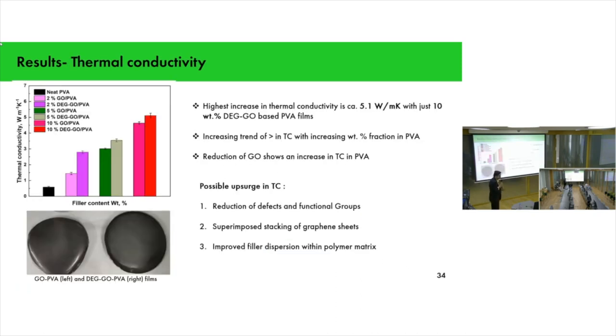So going into the thermal conductivity, our system exhibited extraordinary thermal conductivity, 5.1 watts per meter Kelvin, with just 10% filler in the DEG-based PVA system. So what's the mechanism for that? The mechanism is that after you reduce it, there is a reduction of defects and functional groups. When you are reducing the functional groups like OH groups and carboxyl groups, you are actually pulling the graphene flakes closer to each other through van der Waals forces. And moreover, our system also had improved filler dispersion within the polymer system.